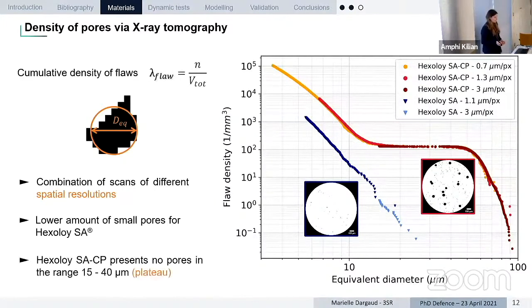What you can see is that first, the material Hexoloy SA seems to have a slightly lower amount of small pores compared to the other one. And the Hexoloy SA-CP presents this very large plateau, which actually translates the fact that in this material we don't have almost any pore between 15 and 40 micrometers of equivalent diameter.